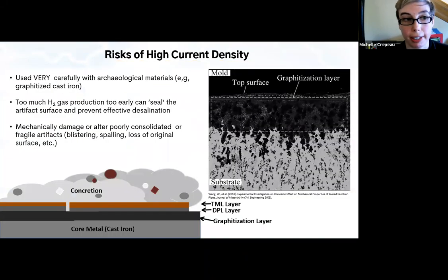But the risks of high current density have to do, one, with too much hydrogen gas being produced too quickly and too early, which can basically seal the artifact. Reduction happens so quickly that you cut off the ability for chlorides and other things to leave. You fill in all those holes that I mentioned with reduction product extremely quickly. And then you can't desalinate your artifact as well as you would like.